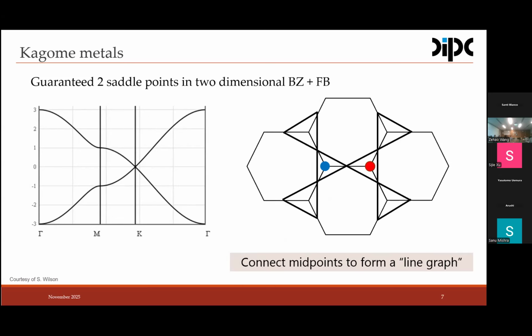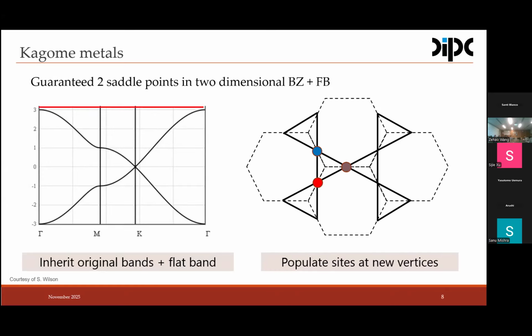the middle points of this honeycomb lattice and form a line graph, and start to populate the corners of the triangles, we end up with a tripartite lattice, which inherits the van Hove singularities at the M point and the Dirac crossing at the K point from the honeycomb structure, plus one flat band, or actually the number of flat bands depends on the number of sites in the bipartite or tripartite lattice.